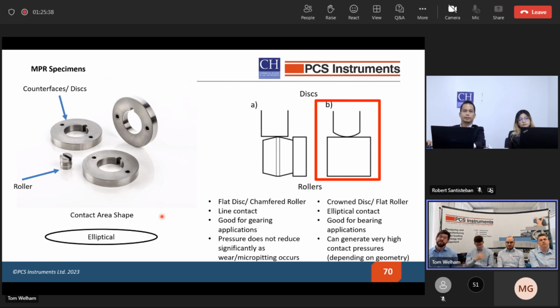However, other contacts are used as well. So we also have crown discs. We have a radius on the disc surface, and this gives us an elliptical contact when run against a flat roller. This is more applicable for bearing contacts, and we can generate much higher pressures. We can actually vary the crown radius to extremely small radii to generate high pressures such as 4 to 4.4 gigapascals, whereas the line contact will probably end up generating more like 2.5 to 3.